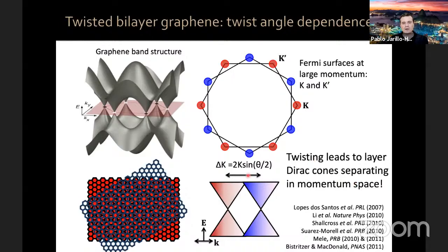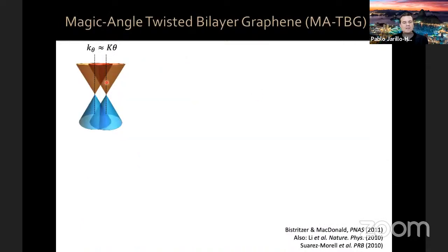Now, let's look a little bit more in detail at this situation. Let's start with an angle which is already small enough such that the sine of the angle is equal to the angle. The Dirac cones would look like this and they would interpenetrate each other if electrons in one graphene sheet didn't know that the other graphene sheet exists. However, because when we put two graphene sheets on top of each other, these are only three angstroms apart, there is actually interlayer tunneling.